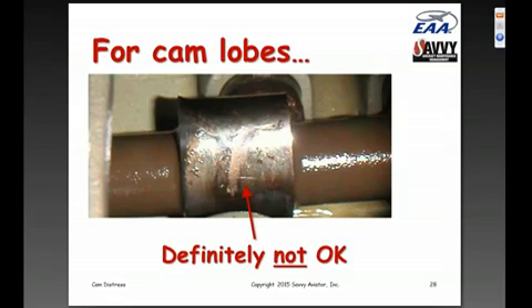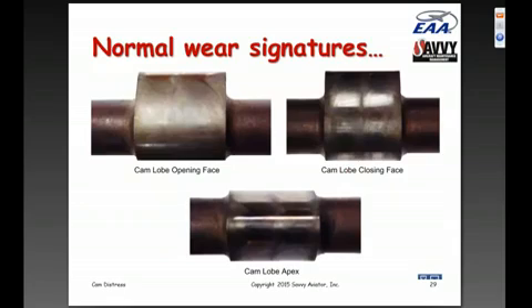Now, usually the way we get to look at a cam lobe is when a cylinder comes off, as I recall. I'm just getting ahead of myself for a second. Here are some other pictures that came out of the Continental Service Bulletin showing normal wear signatures on a cam. This is what a cam that's been in service for a while should look like. And you can see the wear surfaces are shiny, and they tend to be a little bit scalloped because of the way the lifter contacts various areas of the cam as it rotates.